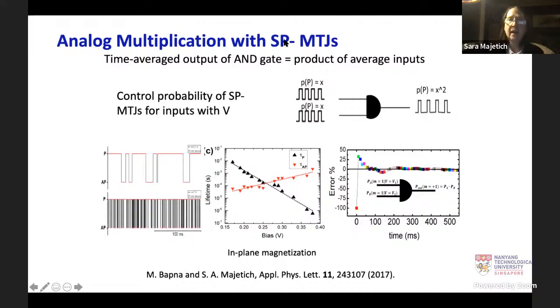And if we look at the application of analog multiplication, what we find is that if you look at the time average measured over a very long time, you get a very good approximation to this product. If you're measuring over a smaller number of cycles, there is some error, but that's saying that you really want devices that are switching with low energy barriers. So you're seeing that the average time is very small between switching events.